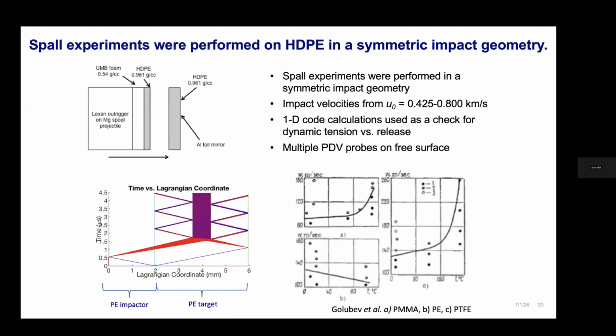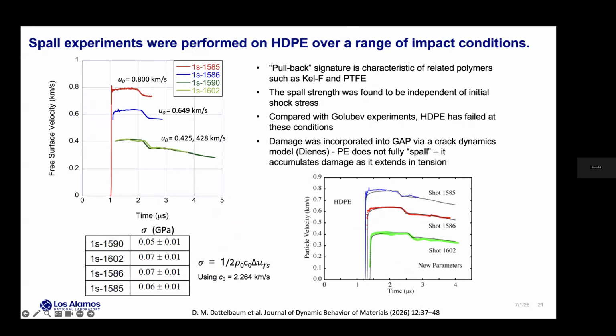So we do these experiments in a symmetric impact configuration. We use a polyethylene impactor impacting a polyethylene target. Just for time, to make sure we have time for questions, I'm going to go kind of quick through this. But we did spall of high density polyethylene at a variety of conditions. And again, this is what the wave profiles look like, where you don't see that reverberation at high velocities. You just sort of see this drawing. You don't see any waves reverberating in the material. And you might see something when you go down to lower velocity, some evidence of a pullback signature.